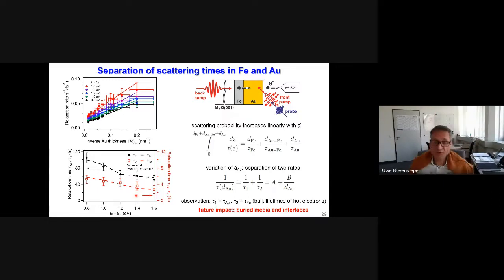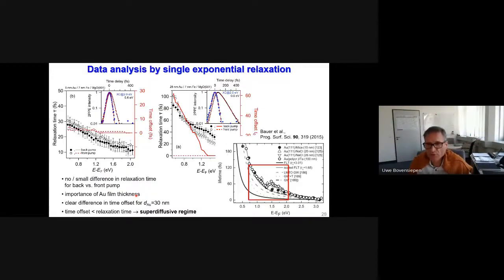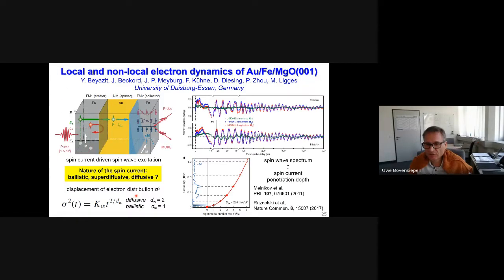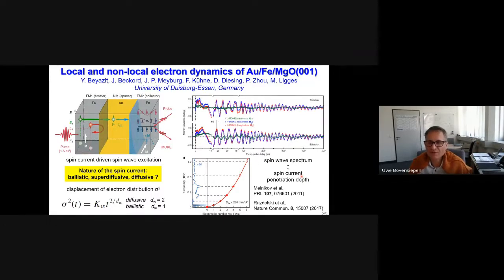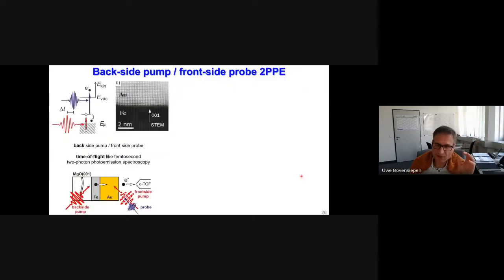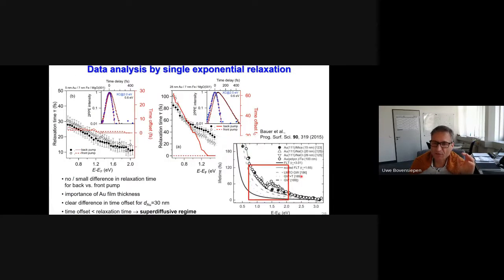Okay. Yes, this is a very good point. We have done previous work that I just quoted here, so please look into this work, for example. There we have used optical magnetic second harmonic generation to probe the spin-dependent response on the gold surface upon injection of spins from iron onto the gold surface. And we clearly see even the magnetic hysteresis of iron imprinted on the gold surface if you look at the proper time delay.